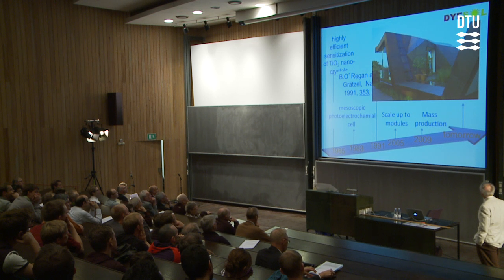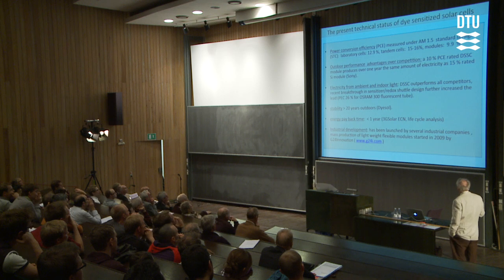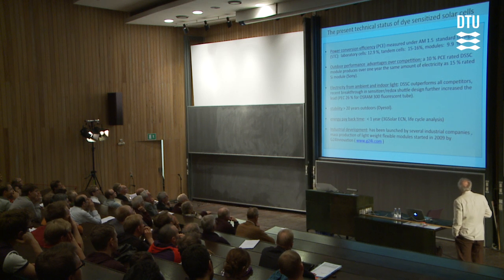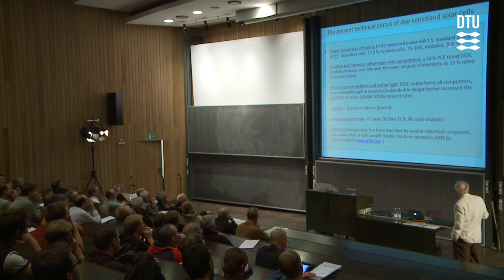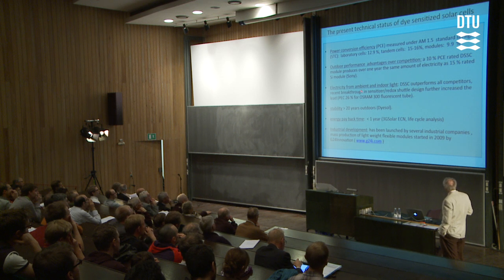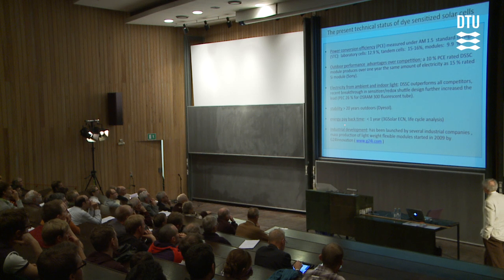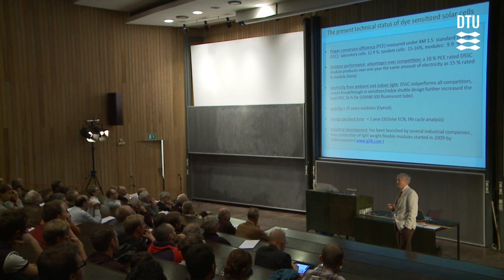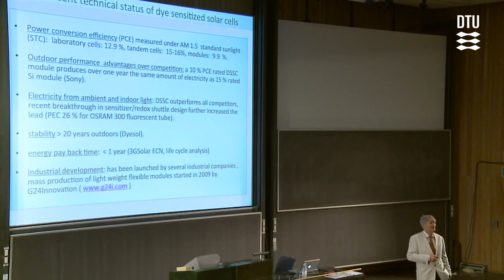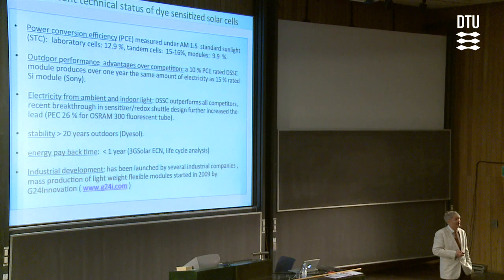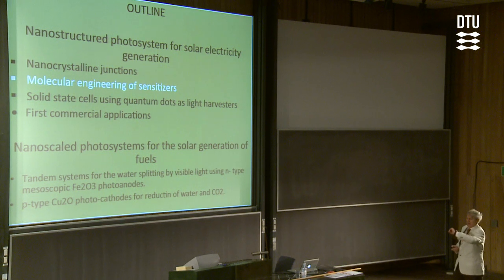There's another branch that developed in the practical sense of building-integrated photovoltaics. The module efficiency is 9.9% certified. We have an advantage indoors. Energy payback time is very short. The plant in Cardiff uses a windmill to provide power for the production, putting the carbon footprint below 6 grams per kilowatt hour — 10 times less than the silicon cell.